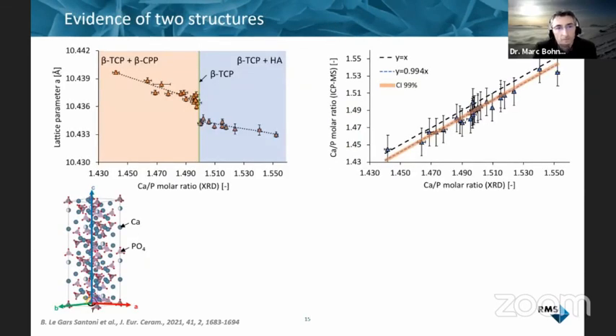And so he did an intensive Rietveld refinement analysis of these powders that he produced. You have here the calcium to phosphate ratio, and here the lattice parameters of the beta-TCP. In this area, you have a bit of calcium pyrophosphate impurities. In the high range of calcium to phosphate ratio, you have a hydroxyapatite. And actually, we would expect that the lattice parameters are constant for beta-TCP because there's only one structure. And we saw this shift of lattice parameters and a jump at 1.5.